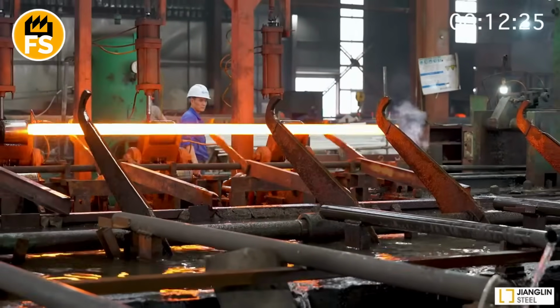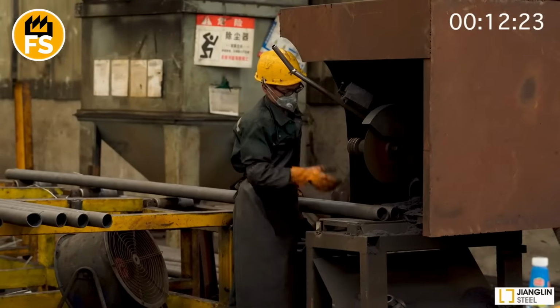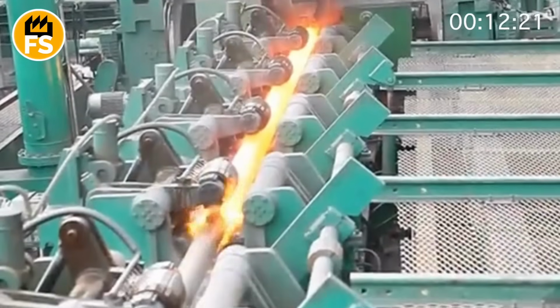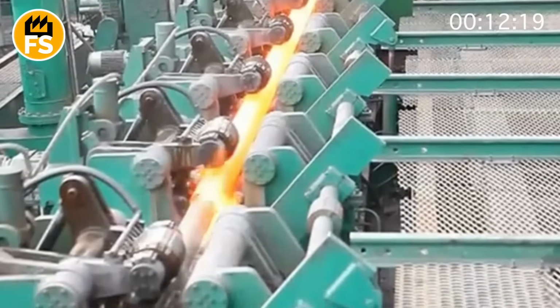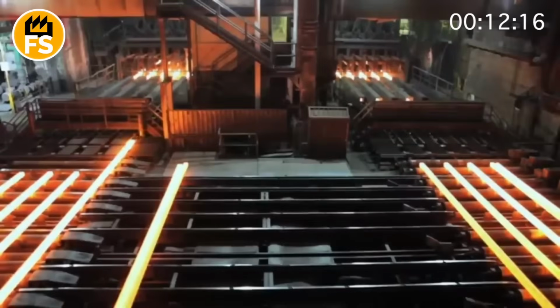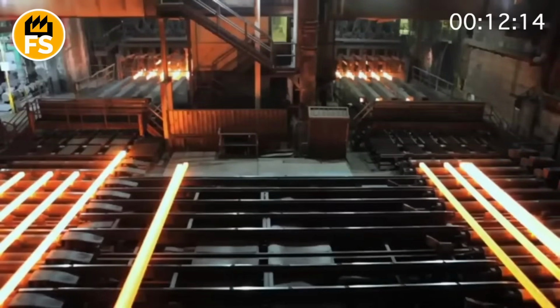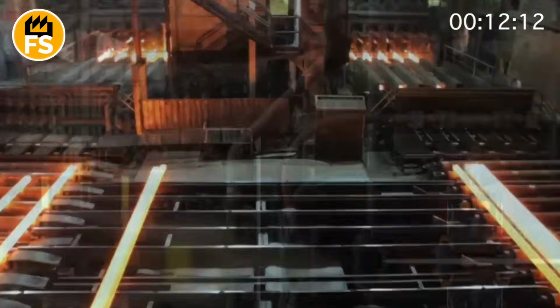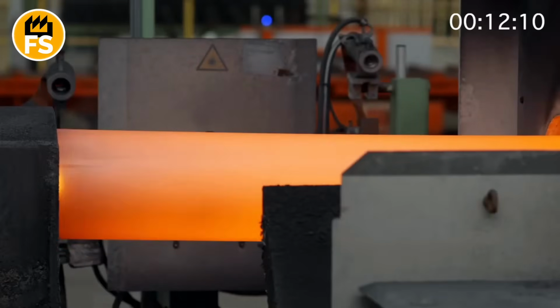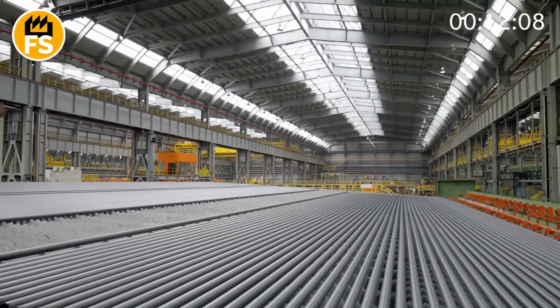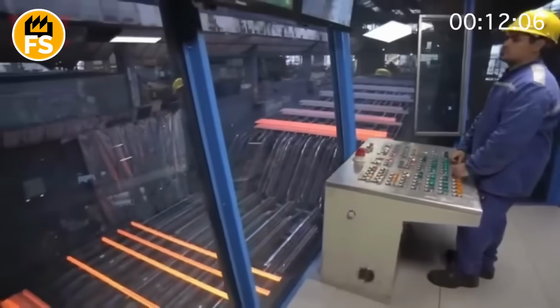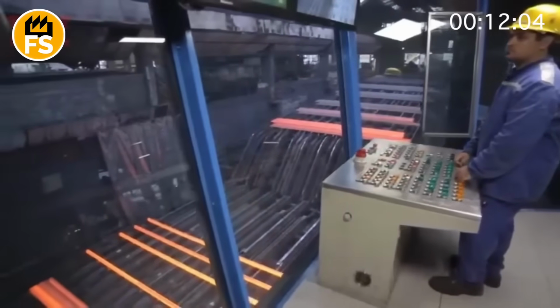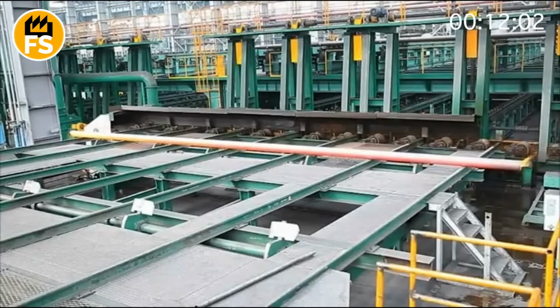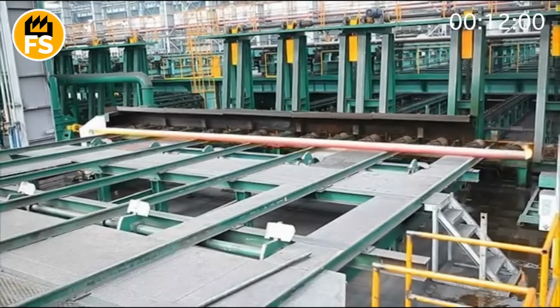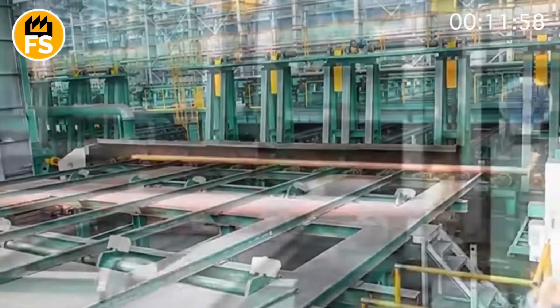The red-hot billet is placed on a special support ring in front of the piercing mill, where a thick, cone-shaped rod awaits it, the so-called piercer point or piercing mandrel. At this moment, immense force is at work. The billet is rotated between two conical rolls, spinning in opposite directions. The rolls don't just squeeze the billet, they create strong rotational and axial pressure, causing the billet to stretch along its axis, flowing around the piercer point.